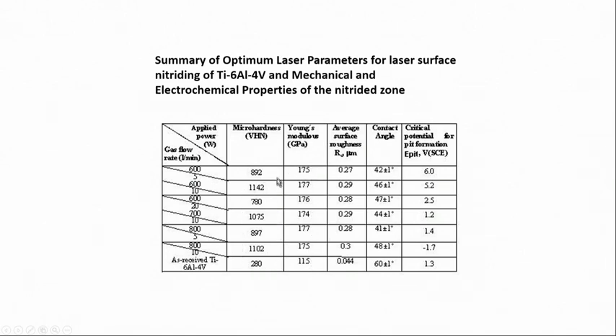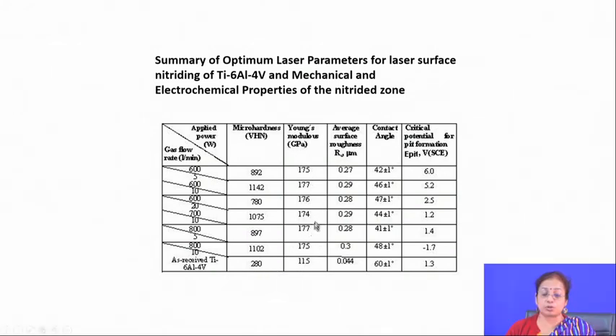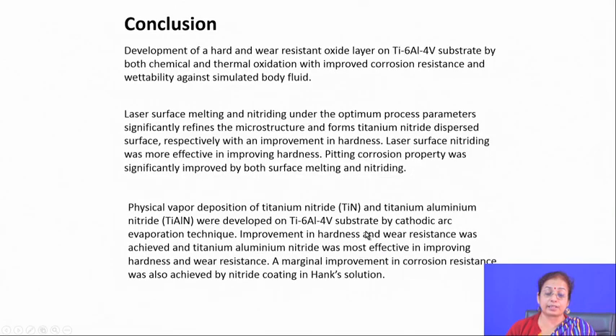One interesting problem related to this nitriding operation is that because of nitriding there is an increase in the Young's modulus of the surface, but again that is on the surface only. So, it might not be so important for that specific application, but the contact angle was reduced to a large extent. The critical potential for pit formation again was found to vary with the process parameters, and it was increased. So, you can say that pitting corrosion resistance also increases because of the nitriding operation.